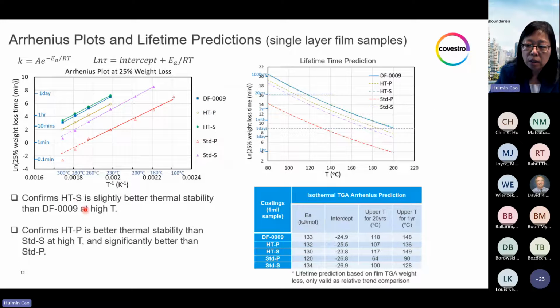And why are we testing in this extremely high temperature condition? It is for Arrhenius study, where you do accelerated lab testing at a temperature range much higher than your application temperature, in our case up to 300 degrees C, which makes it possible as a short-term test. Based on the Arrhenius equation, with a straight line fit, you can predict the lifetime in your field application at lower temperature. And the Y axis is the log scale of the time when reaching 25 weight percent loss, which is defined as a failure criterion commonly used in the literature.